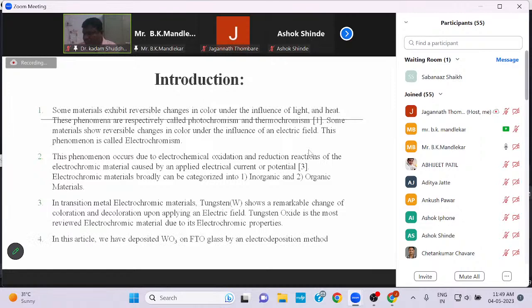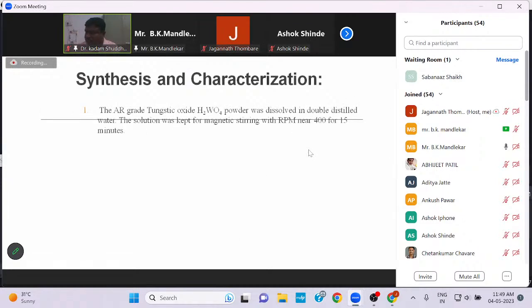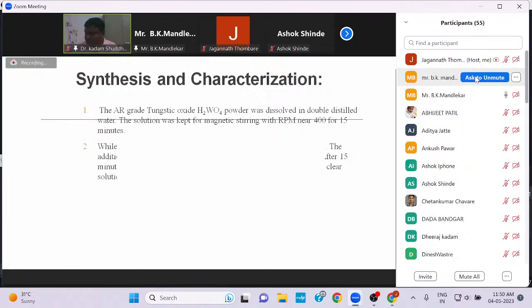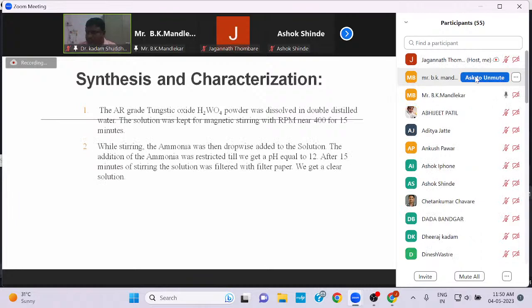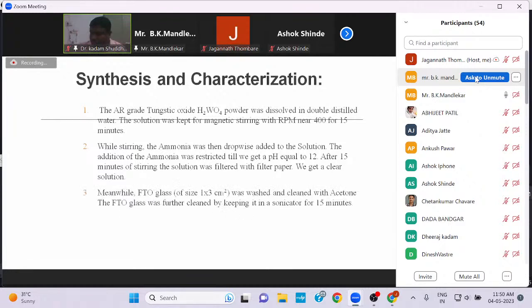In this article, we have deposited WO3 on FTO glass by electrodeposition. This is how we have synthesized it. We took AR grade tungstic acid powder and dissolved it in distilled water, stirring on a magnetic stirrer at 400 RPM for 15 minutes. While stirring, ammonia was added dropwise to change the pH to 12. After 15 minutes of stirring, the solution was filtered with filter paper and we got a clear solution.